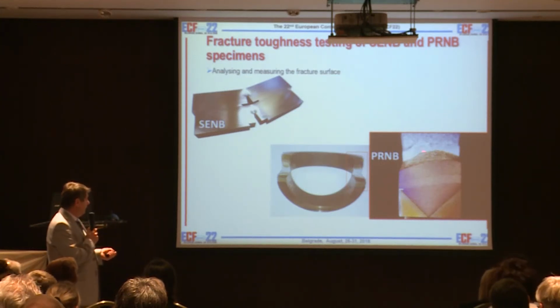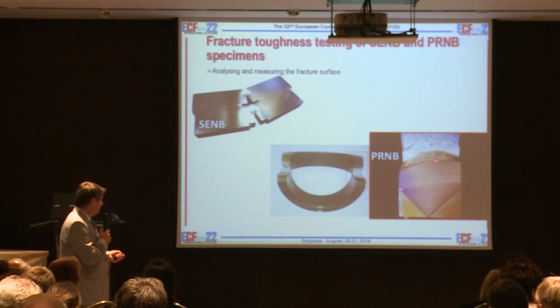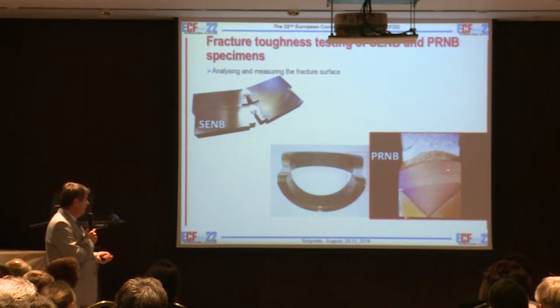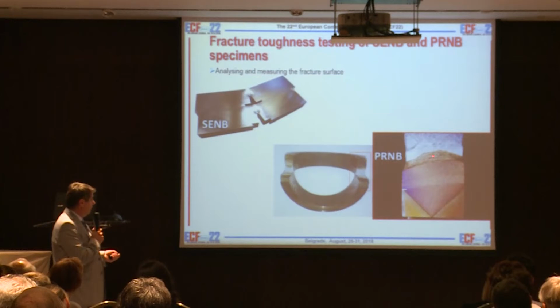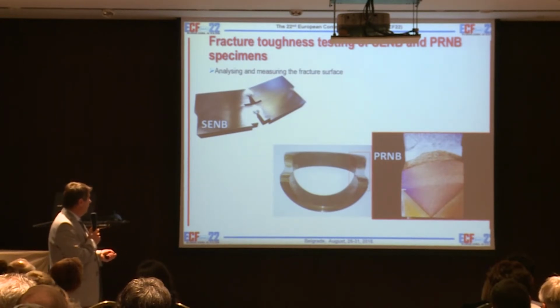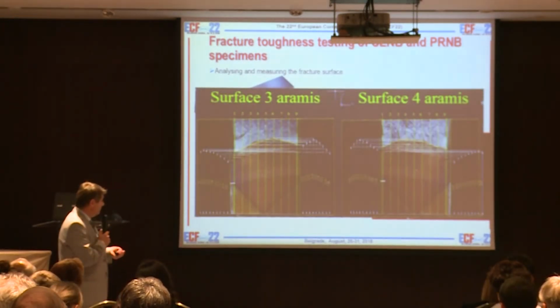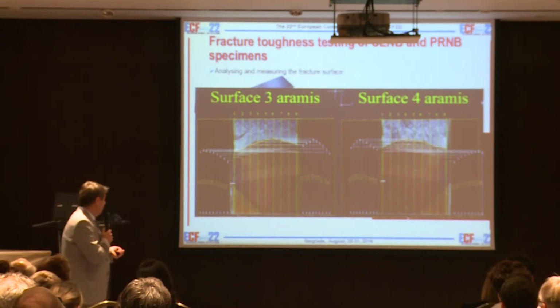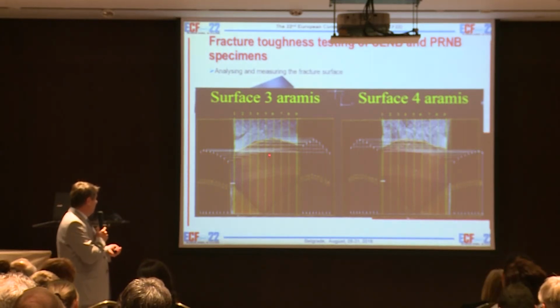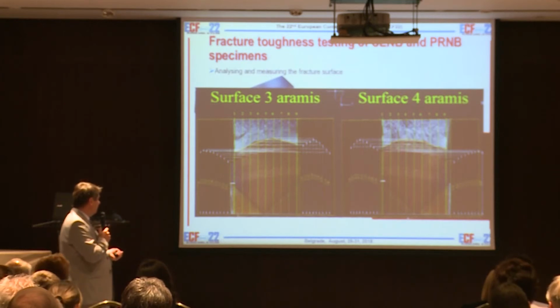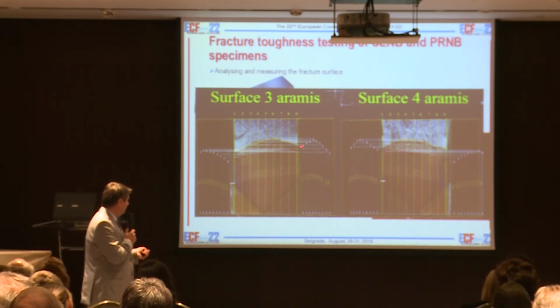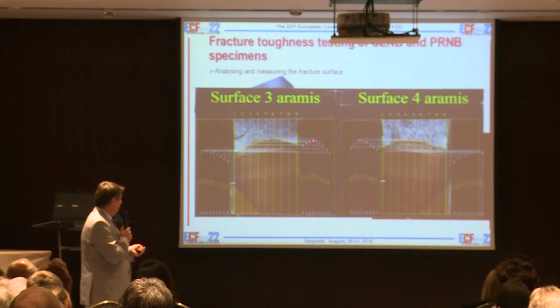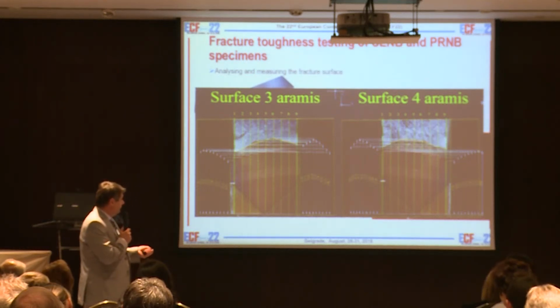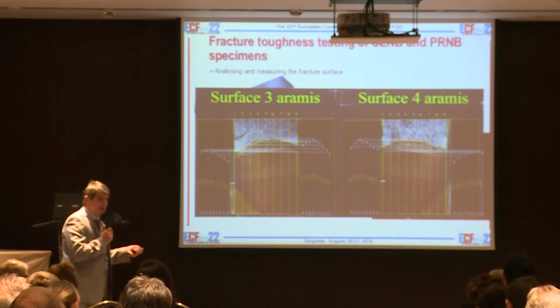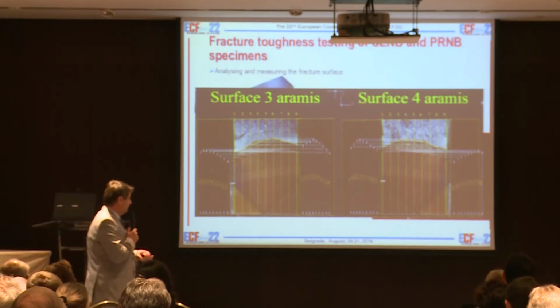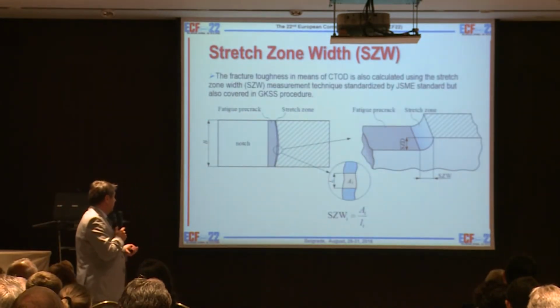And here is our pipe ring specimen with heat tinting in order to mark the start of crack propagation extension. This can also be measured according to the standard at 9 points, so that we see what we get for the initial crack length and for the extension, the final crack front, and then these results also go into the analysis. Of course, these are not standard results, because deviations are more than 10%.